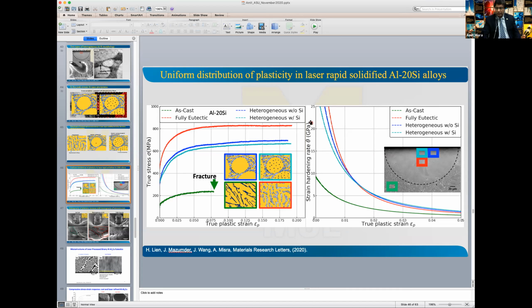Sometimes you'll see grain growth during a test, and there can be other things. You can see reversible plasticity. A lot of things can happen when you have very fine scale pure metals. Especially when you have composite metals, there's less chance, because the real interface is a boundary between, say, copper and a refractory metal. As long as that is pure and not amorphous or something, it should be resisting deformation.